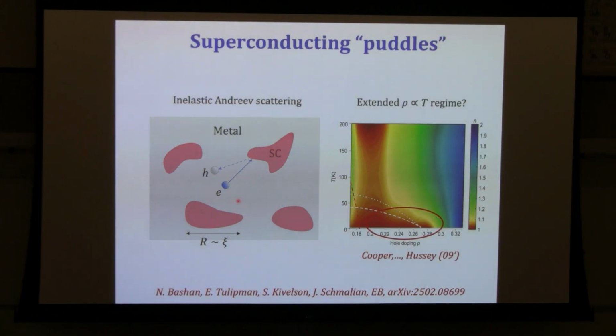Now, an important comment here. If we have these superconducting puddles they can also Josephson couple to each other. So in addition to scattering the electrons from the metal, these puddles can actually carry a supercurrent just by locking their phases together. We're imagining that we're far enough from the critical field, and as we'll see, the superconducting phases of these puddles are quantum fluctuating enough that we can actually neglect the Josephson coupling between these puddles. So the model that I'll sketch treats a single superconducting puddle coupled to a metallic environment, and I'll study the Andreev scattering rate of electrons off this puddle. I'll basically imagine that all the other puddles are far away enough that they don't interact.